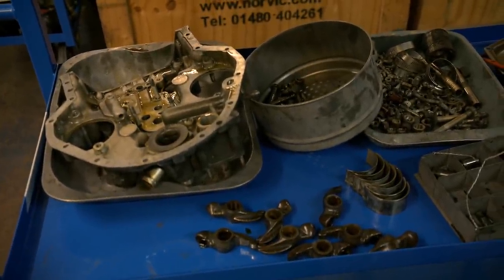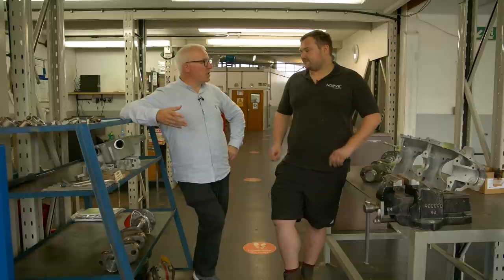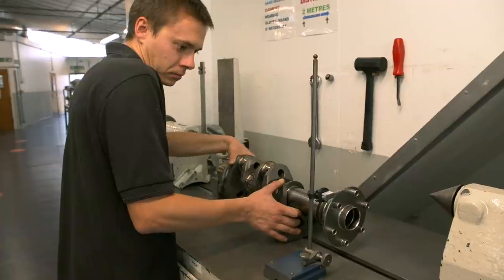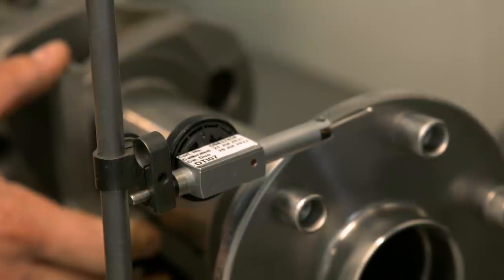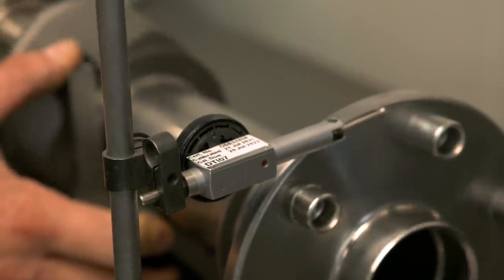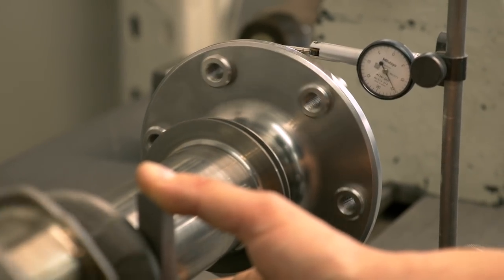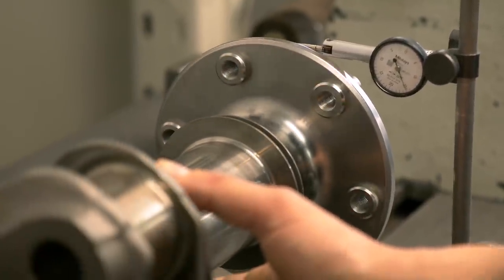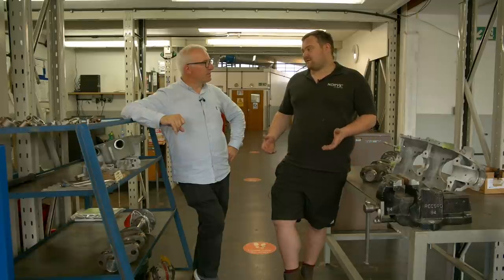What sort of testing are you doing on these components? First we do a visual and a dimensional check, and then we'll do crack testing. For visual and dimensional, we look at the condition of the component and if there's any visible damage. Then we would do run-outs and parallelism checks of different components. So the run-out of the crankshaft — we would check that the flange or the spigot wasn't bent, and that no journal has gone out of round from the shock load force. Mostly they pass, but depending on how significant the shock load was, crankshafts do seem to be the most susceptible.